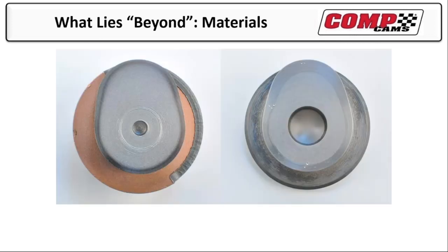Here's the other thing about when I talked about heat treat depth. The cam on the left is an 8620. You can see the copper masking. You can see the heat case depth on it. It's only about 100 thousandths. And then you can see it starts getting really fuzzy.